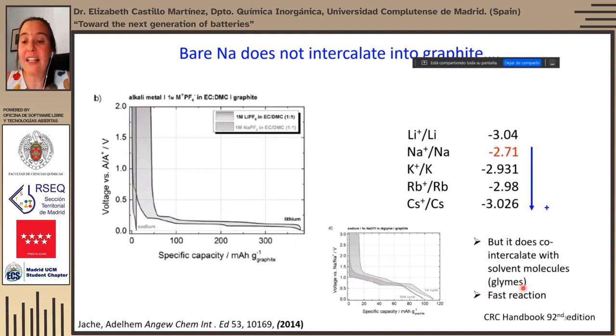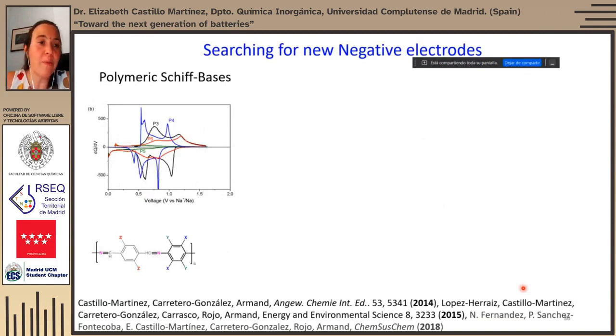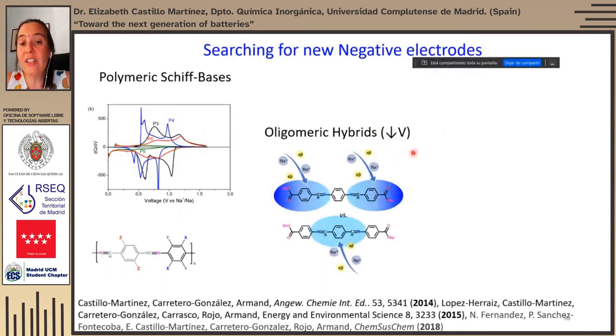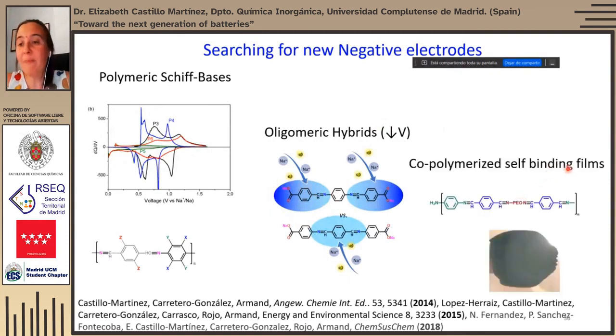The fact that graphite doesn't intercalate sodium ions has motivated lots of research to search for alternative anode materials. And I'm going to show you an example of my own research here, where we prepare polymeric Schiff bases and propose them as electrode materials. And actually, we saw that the redox processes, two redox processes, which change in voltage with the change of substituents, of course, do take place at voltages close to 1 versus sodium plating. And therefore, it's interesting for anode material for sodium ion batteries. We could also go to lower voltages if we hybridize these Schiff-base-based units with carboxylates, or we could even make self-binding thin film by copolymerizing the Schiff-base-based functionality with polyethylene oxide unit.